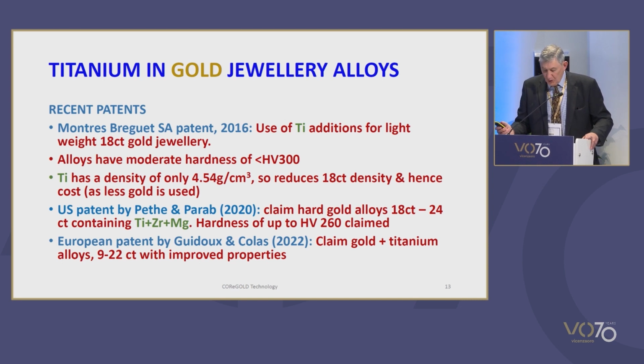With a density of only 4.54 grams per cubic centimetre, its use in alloying with gold can make a significant impact on alloy density and hence cost of jewellery. In another patent, a US patent in 2020, the inventors Pethe and Parab claim hard gold alloys of 18 to 24 carat containing titanium, zirconium and magnesium in combination for jewellery manufacture, again with a beneficial impact on alloy density. Hardness values of up to 260 Vickers are claimed.